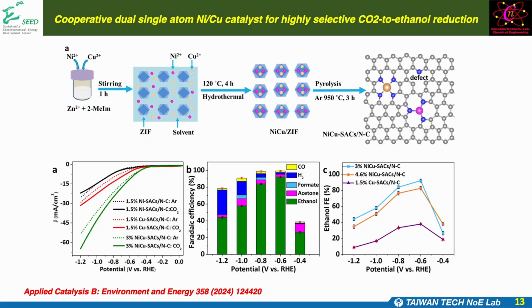The final example is, of course, nothing to do with hydrogen production, but how we can use power to X to produce valuable chemicals. Here we produce a dual single atom, this copper nickel single atom, and we perform CO2 reduction. Interestingly, we can get a very high ethanol Coulombic efficiency of around 83% at the voltage of minus 0.6.